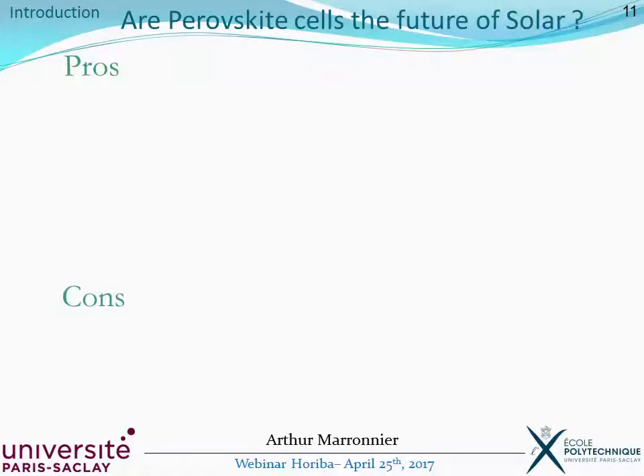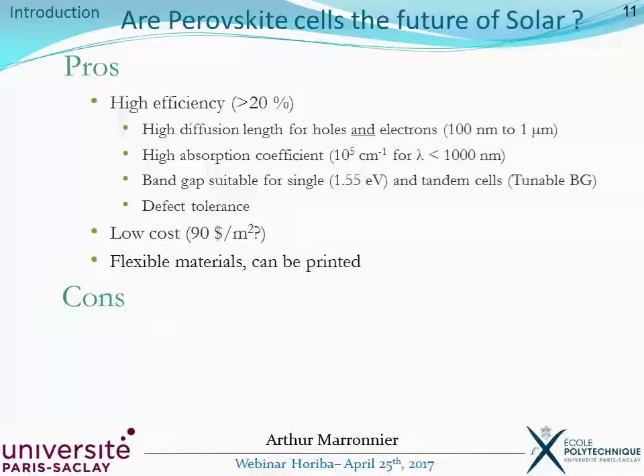So are these perovskites the future of solar? Well, they have pros and cons. As I said, they are highly efficient, and there are many explanations for this fact. They have a very high diffusion length, both for holes and electrons, which is quite remarkable. And this length goes from 100 nanometers to around 1 micrometer, depending on the structure. They have a high absorption coefficient, even for a wide range of wavelengths.